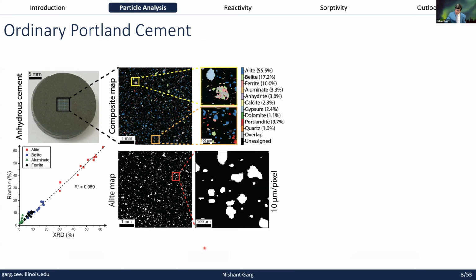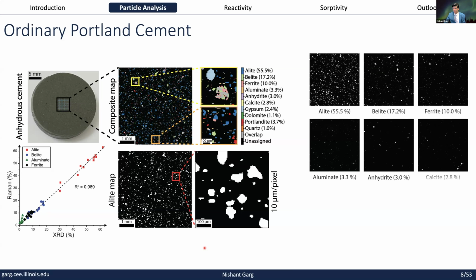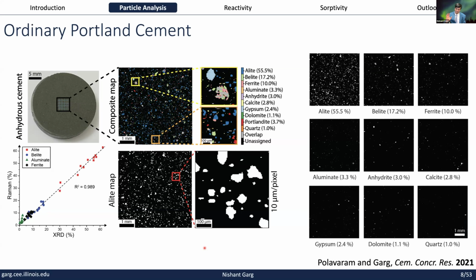In principle, you can do the same thing with SEM EDS, and there has been a lot of good work done over the past few decades, starting from NIST. But here it becomes highly complementary, because now instead of relying on the elements to come up with a mineral stoichiometry, you can directly map the mineral as well as the polymorphs. So you have individual mineral maps of all the phases, even something like quartz, which is an impurity in this system, present at 1%, and you can see that, right?